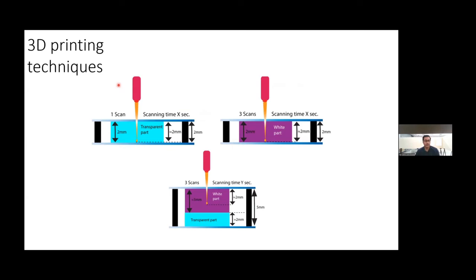In this technique, we optimized the scan number and also the scanning time. You can see here for a 2 millimeter silicon spacer, with one scan we can create this 2 millimeter transparent part, only the transparent part. And with 3 scans, we can create this white part, 2 millimeter. But if we use a 5 millimeter spacer and 3 scans, then we can create approximately 3 millimeter white part and 2 millimeter transparent part. This is the optimized technique for making the bilayer.